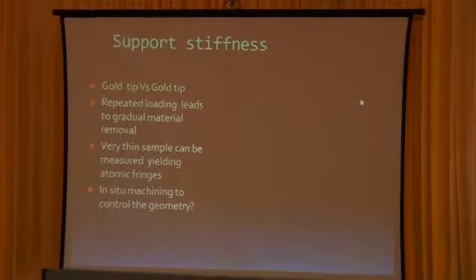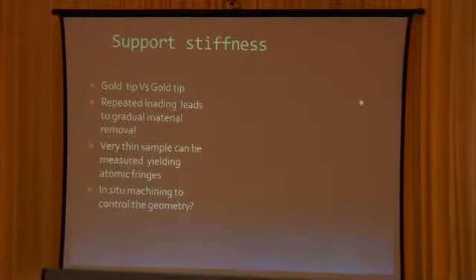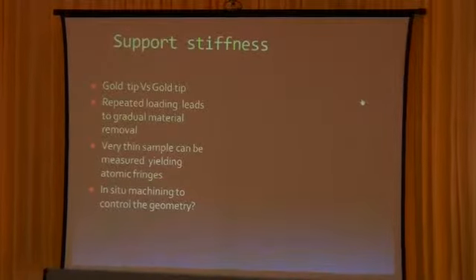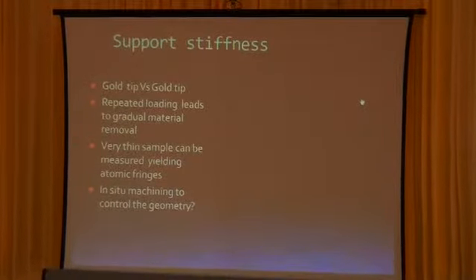and we were able to manage to get it by making these devices extremely small. The whole device is about the size of a pen, which goes inside the transmission electron microscope, and it is in high vacuum. You can see there is no vibration. Those who have worked in TEM know that if you go and tap on the table anywhere in the room, you can see your sample vibrating. They vibrate on the order of hundreds of nanometers. We can't do experiments like that. The tip will go out of contact. So these are extremely difficult experiments which have to be done in the middle of the night when no lorries are going along the road of IISc.